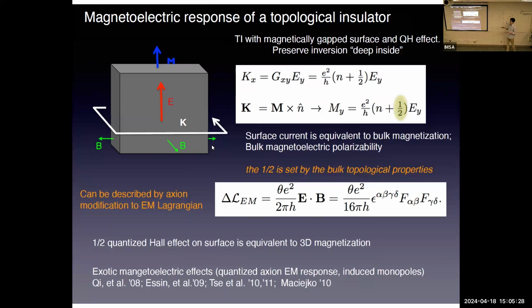So yeah, if you think of a thought experiment, you have a slab of a TI where the magnetic field is going outward on every surface, and you apply an electric field. If it was a perfect TI, you would expect that it will develop a circumferential current. But you can also think of this current as a bulk magnetization. And if you do this simple algebraic manipulation, you can find out that the y component of this magnetization is equal to this electric field multiplied by some constant. And in case of TI, it happens to be this very quantized value.